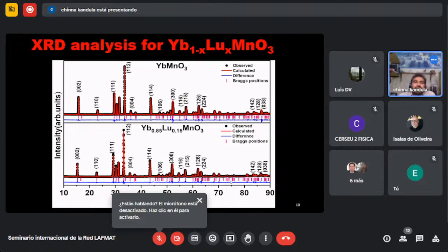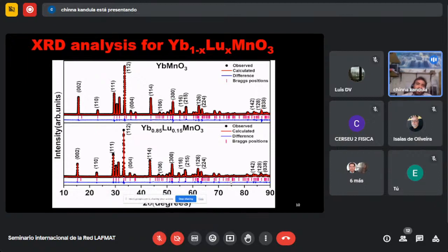You can see here, the first figure at the top is YbMnO3, the parent compound. I synthesized that in my laboratory, and I also did Rietveld refinement for this using the X'Pert HighScore Plus software, which is available in our university. There is no extra peak, which means the sample is perfectly formed. After Rietveld refinement, the majority of peaks are matched, and their Miller indices are also matched with my compound. So there is no other phase. The hexagonal structure is confirmed from the XRD.